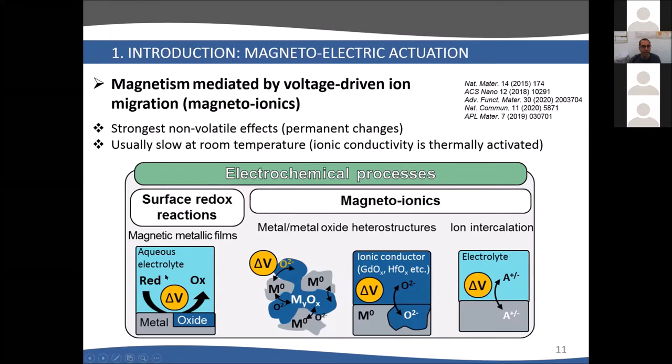There are various ways to do this. You can imagine immersing a metal like iron in an aqueous electrolyte, and you would have some surface redox reactions. Because of this oxidation, you may have changes in magnetic properties. Or you could use a solid electrolyte like gadolinium oxide or hafnium oxide. These are conductors of oxygen ions. When you apply voltage, you can exchange this oxygen between these materials and the magnetic metal of interest. This changes the magnetization, coercivity, and so on.